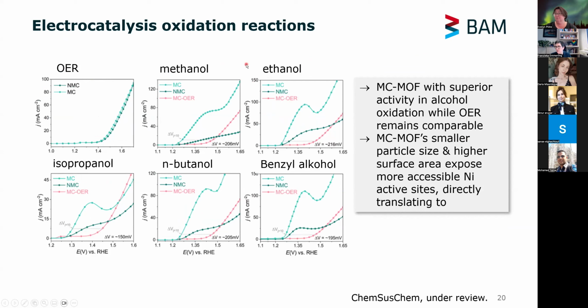and then we see the oxidation of different alcohols. Here in the oxygen evolution reaction, there is not a big difference, but then when it comes to the alcohol oxidation, you can see that there is a pronounced difference, that the mechanochemically derived MOF is performing much better, and that seems to have to do with the particle size and also the higher surface area, so we have more accessible nickel active sites. The alcohol also needs to bind in the first place, and that makes these catalysts more efficient.